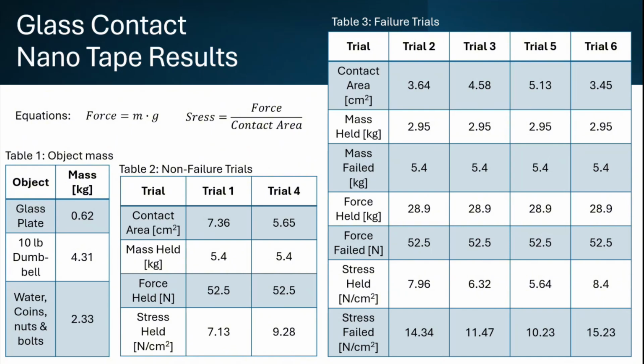And then in our table 2, we have our non-failure trials. These trials were trials where the tape did not fail. So we could see that in trial 1, the maximum stress was 7.13, or the stress that it held was 7.13. Trial 4, the stress that it held was 9.28. Okay, in table 3, we have our failure trials, trial 2, 3, 5, and 6. I added an extra trial here just to get one more data point.